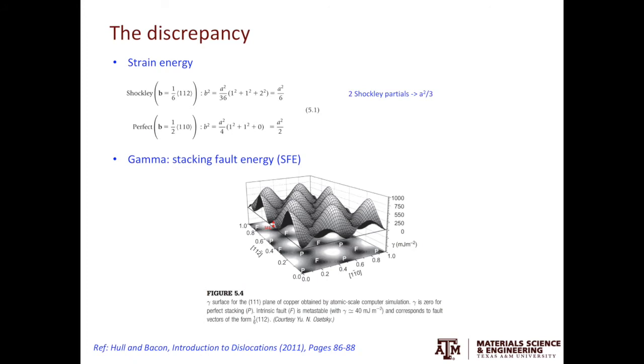There is a discrepancy here. If we look at the strain energy, the strain energy of two Shockley partials is A square over 3, but the strain energy for the perfect dislocation is A square over 2. So the two Shockley partials seems to be energetically favorable compared to one perfect dislocation.